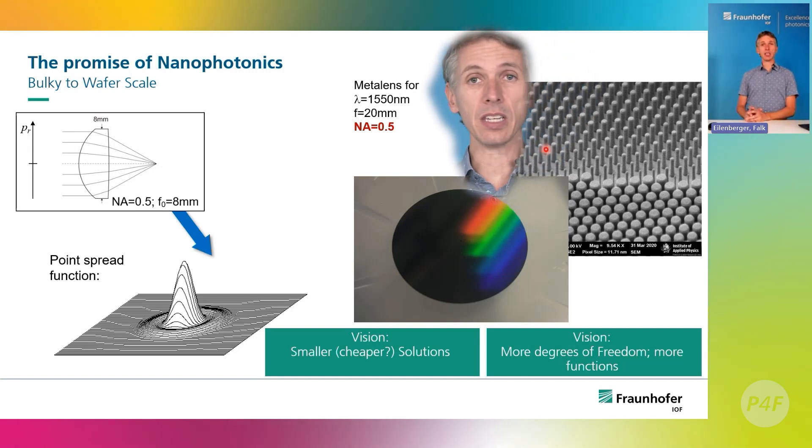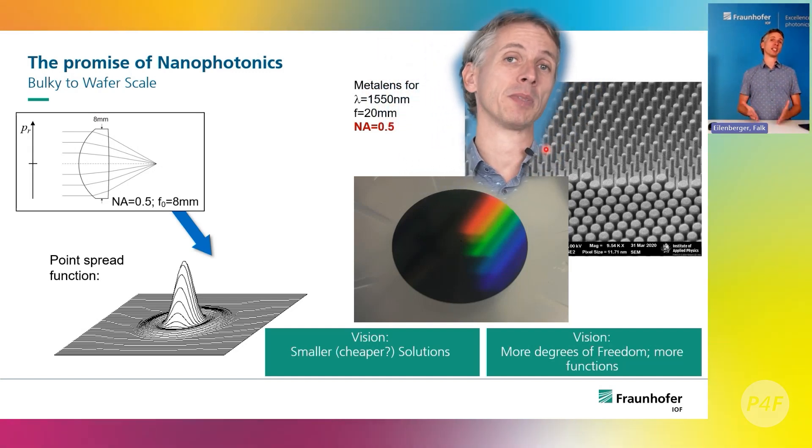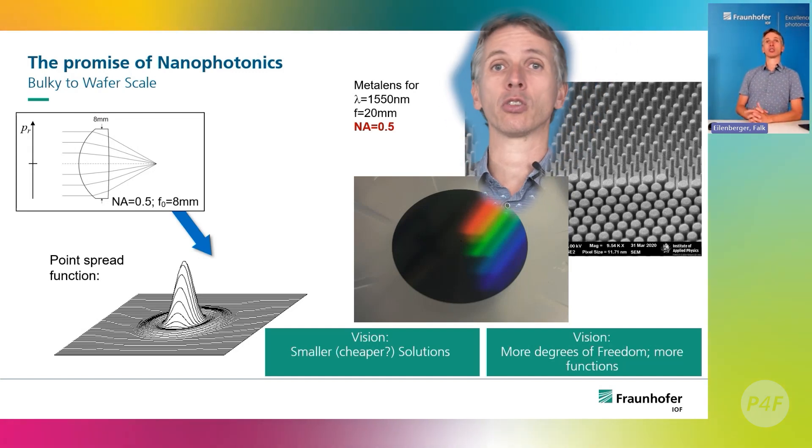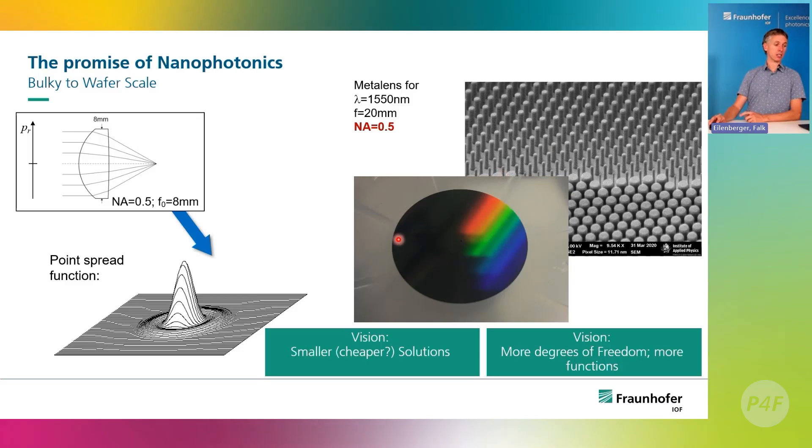This fulfills the purpose of making an optical element flat, but it's also a very complicated way of doing so. A 20 millimeter diameter element has around 25,000 nano antennas in each direction, meaning the whole thing consists of about a billion nano elements. The meta lens is probably the most prominent metasurface component, but it's probably not a good way to go initially, because we have to build very complicated elements to compete with classical lenses that are already extremely well crafted and come fairly cheaply.